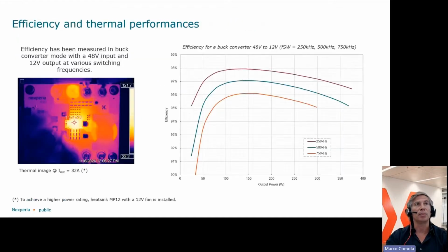So let me go on. I just want to give an idea of the efficiency and thermal performance. The efficiency was measured with a DC-DC converter, 48 volt to 12 volt, so the board was used as a buck converter. On the right side, you can see the switching frequency changed from 250 kilohertz to 500 kilohertz and 750 kilohertz. You can see the curves there, the efficiency versus the output power. You can easily see the efficiency is quite good: it is more than 95%, and the output power is very close to 350 watt.